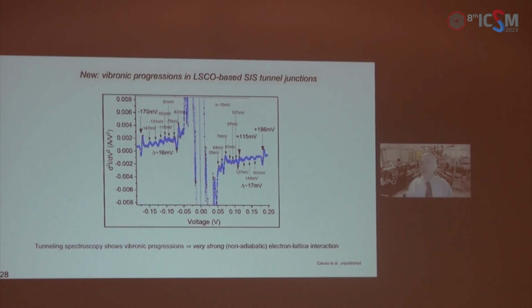But these models are not thermodynamically viable, because if you keep adding charge to the copper oxygen plane and you don't compensate it in any way, then in the thermodynamic limit, the energy will be infinite. So these models are simply thermodynamically not viable. The copper oxygen plane is charged, with a charge of minus 2e, and it has to be compensated, made charge neutral.